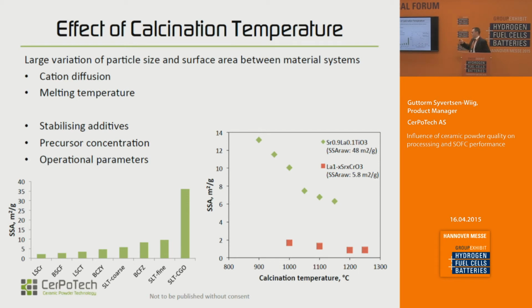So basically different materials have different properties due to thermodynamics and kinetics, because you have cation diffusion and the melting temperature, and these physical properties play a role. Down on the left here is a comparison of different materials calcined at approximately the same temperatures, but you get all the way from a specific surface area of 1 or 2 square meters per gram up to 30, 40 square meters per gram, just by changing the composition. Also here on the right, you can see the effect of calcination temperature on the specific surface area of a couple of materials.